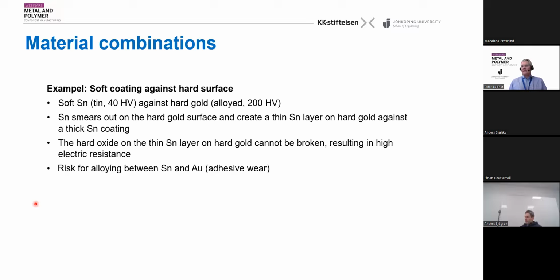And tin will form an oxide film. So on the gold coating, you will actually have a sandwich with hard gold, thin, very soft tin, and on top of that, the hard tin oxide. And since the smeared out tin is so soft, or not soft, but so thin, then you cannot really break the oxide, and that will increase the electric resistance. And then, of course, you can say then we increase the contact force, but then there might be a risk that you actually start to have micro welding and alloying between the tin and the gold. So this is not a popular combination.